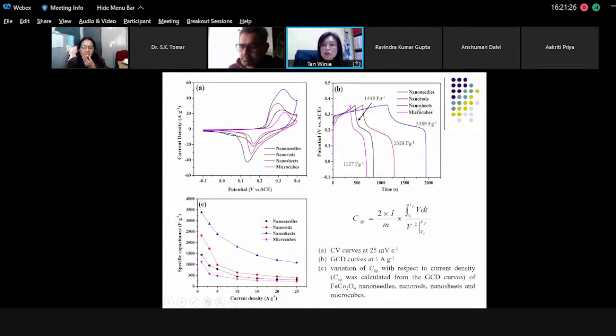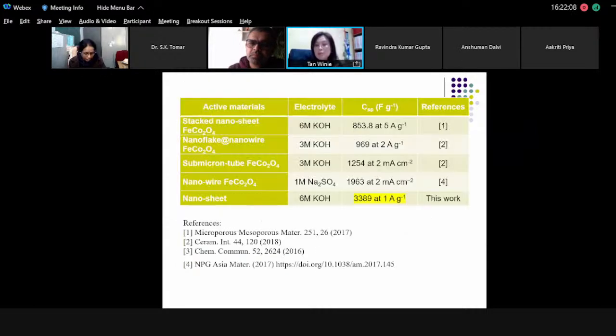We can still see the nanosheets show the highest specific capacitance, which is now 3000, I cannot see clearly, 3000 plus farad per gram. So among all these morphologies, the nanosheets show the highest specific capacitance at all current densities. Maybe this is due to the highest specific surface area and pore volume of the nanosheet structure. It means that they have more active electrochemical reaction sites and greater diffusion kinetics within the electrodes for this iron cobaltite. This table shows the specific capacitance obtained by us as compared to other reported literature. As you can see, we show a more superior performance than those reported in the literature.